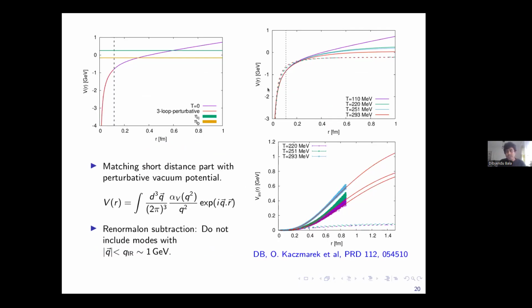Here I show this potential again, but now we compare with the perturbative calculation. This dashed line is what you would expect from the perturbative calculation, and this continuous curve is what the lattice gives, and you see the huge non-perturbative effect here. And in the case of the imaginary part, I show you that the perturbative imaginary part is much smaller than what you would expect from the non-perturbative value. So really lattice is useful even in this temperature range to predict the potential.